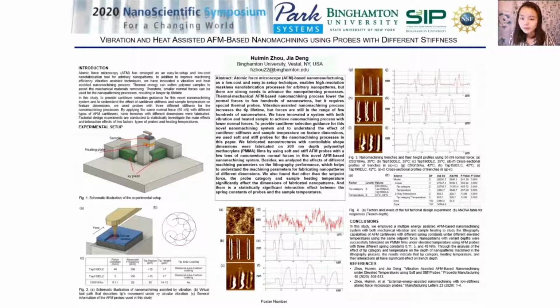B. If no XY vibration is applied in the nanomachining process, the trench size is going to be the same as the tip size. However, when we apply 2 sine signals with the same frequency, amplitude, and 90-degree phase difference on X and Y piezo, a circular vibration is generated on the sample, and therefore the trench size increases. The high-frequency vibration and adjustable amplitude enable high-speed nanofabrication and tunable feature size, while the sample heating technique is applied to soften the polymer and therefore decrease the normal force and extend the tip's lifetime.